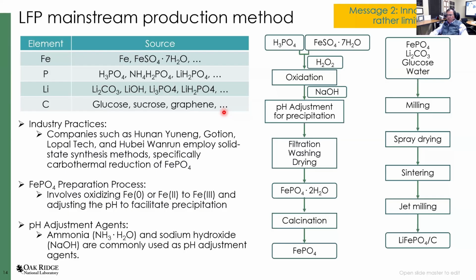Lithium can be lithium hydroxide, lithium carbonate, and others, but we also need carbon because these materials are insulating in nature because they're phosphate, and we need a carbon source to carbon coat them. And in essence, the process starts with some sort of carbothermal reduction of FePO4, if you choose to make FePO4 out of an iron source, and the process to make FePO4 is described here in the middle. It's common knowledge.